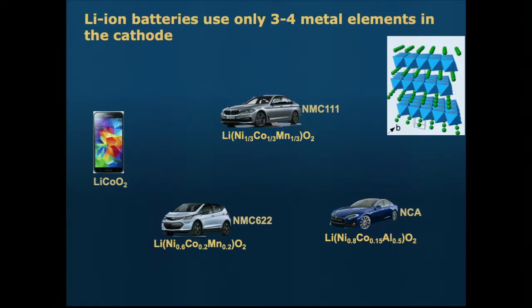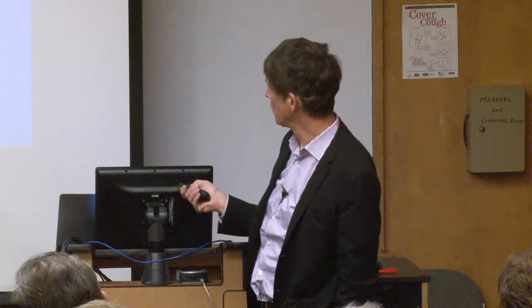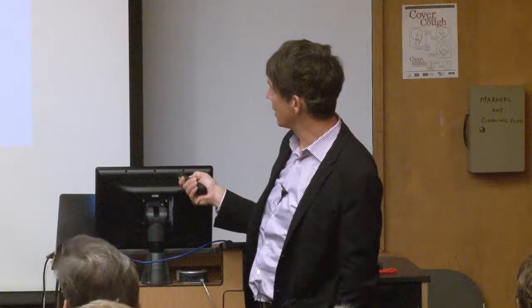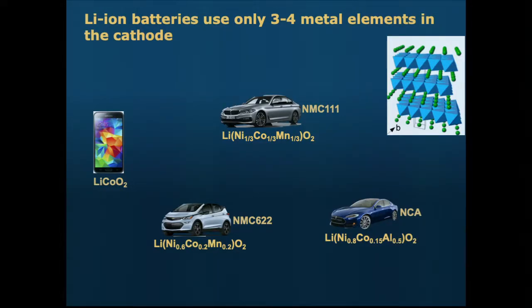But automotive technology uses substitution of cobalt with nickel and manganese, though it's essentially the same layered compounds that I showed you in the beginning. And they go by exotic names like NMC111, NMC622. That just stands for nickel, manganese, cobalt, and the ratio of elements is these numbers. So NMC622 means 60% nickel, 20% cobalt, 20% manganese. This is the staple of the EV industry today. If you buy a Chevy Bolt, it has 622 in it. I would say besides Tesla, most of the market uses NMC622. Plug-in EVs like mine are more like NMC111, so it has a much higher cobalt content.